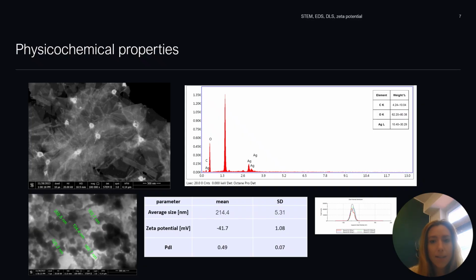The particle size obtained by DLS was consistent with scanning transmission electron microscopy, and the results are here, which confirmed a successful formation of the nanocomposite, revealing graphene oxide sheets decorated with silver nanoparticles. And here are the silver nanoparticles and the graphene oxide sheets. These results demonstrate the successful synthesis of a stable graphene oxide and silver nanoparticles nanocomposite.